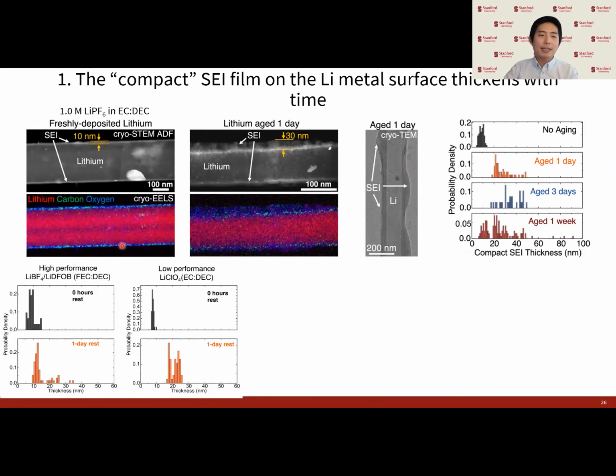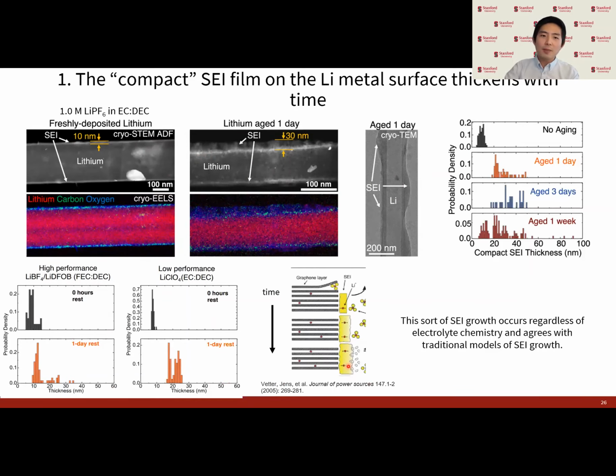But what we see is if we look at these other electrolytes, including this dual salt blend that's good at cycling, and this lithium perchlorate in carbonate, which is both bad at cycling and bad at storage, this kind of trend in this compact SEI film thickening is universal. And this type of compact SEI growth, where you have this slow thickening of this SEI film with time, is fairly in line with traditional models of SEI growth and has been predicted and measured in literature using other techniques.